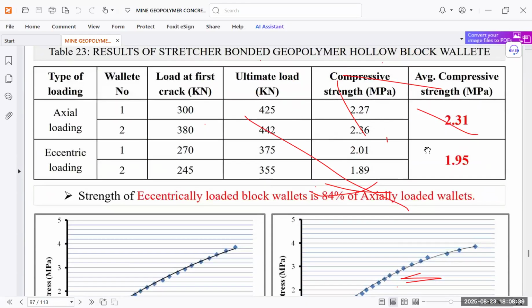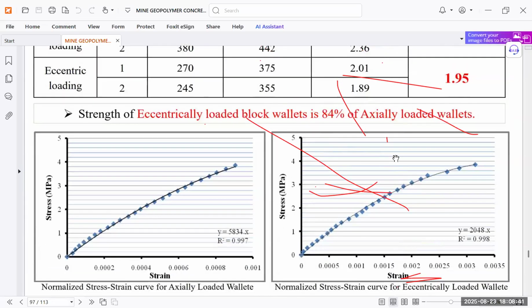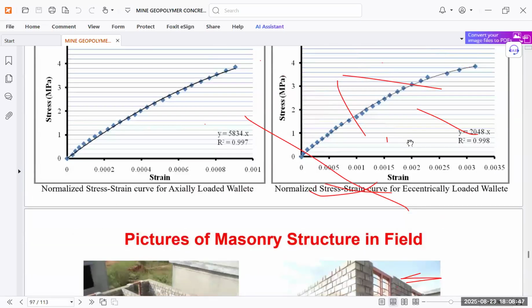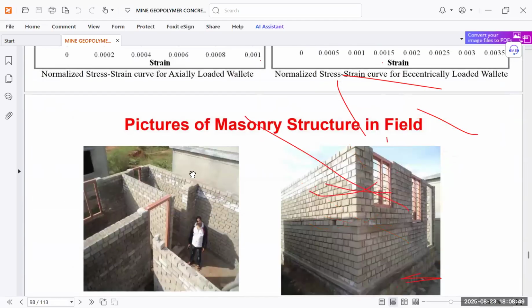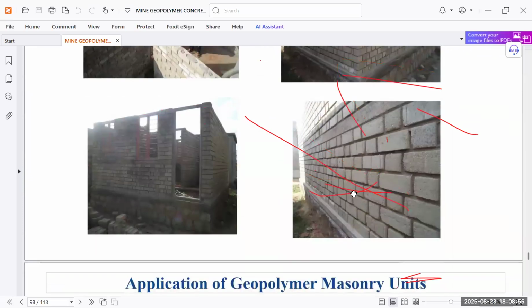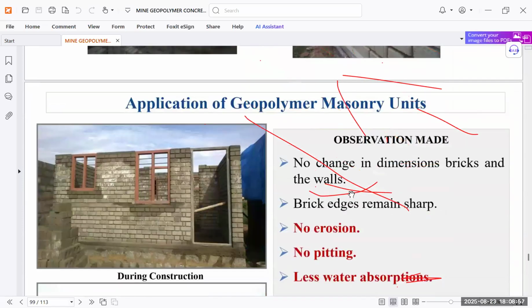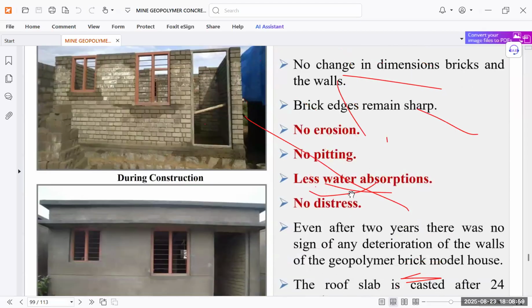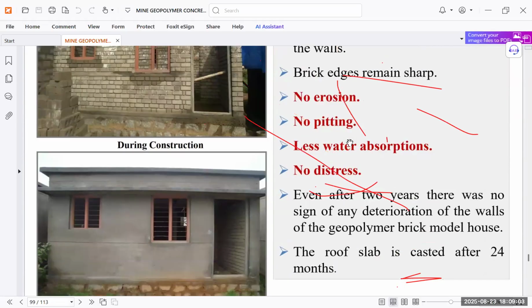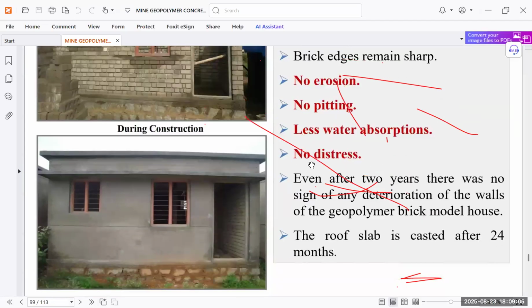Average compressive strength we have seen, axial loading and eccentric loading. And the strength of the eccentrically loaded block wallet is 80 to 84% of axially loaded wallets. This is obtained. So pictures of masonry structures in field. Some buildings have been made with geopolymer concrete. So results are okay as per the requirement. In application, there is no change in dimension of bricks in the wall. Brick edges remain sharp, no erosion. Less water absorption, no distress is there.